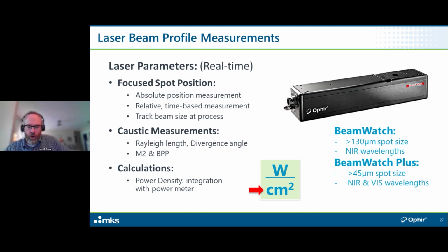Beam Watch, there are two different versions. There's one for beam sizes greater than 130 micron in spot size. It is specifically designed for near IR wavelengths, 900 to 1100 nanometers. And then there's the Beam Watch Plus, which we introduced just recently. It does add the visible wavelengths, so those green and blue lasers, it will measure those. And those go down to more suitable for those single mode lasers at 45 microns and above.